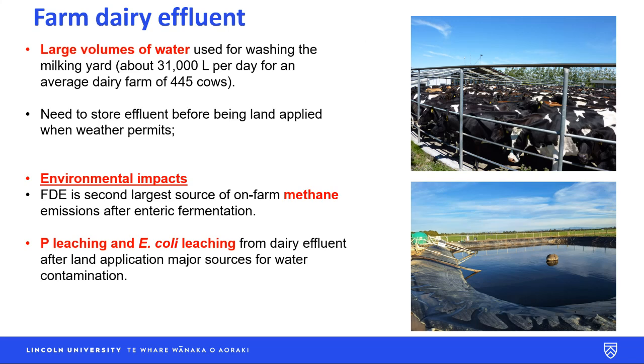You must have enough capacity to store the effluent so that if it keeps on raining every day and you cannot irrigate, you're able to hold it until the weather has improved and the soil is not flooded, so it doesn't cause any leaching losses. So the problem is that during the storage of the effluent in this large pond, methane comes out because there is organic matter in there, and under anaerobic conditions it produces methane. So that's the second largest source of methane after enteric fermentation for dairy farms. And the other thing is that when you then apply the effluent on the farm, as you've seen earlier, it can contribute to phosphate leaching, but also E. coli leaching.